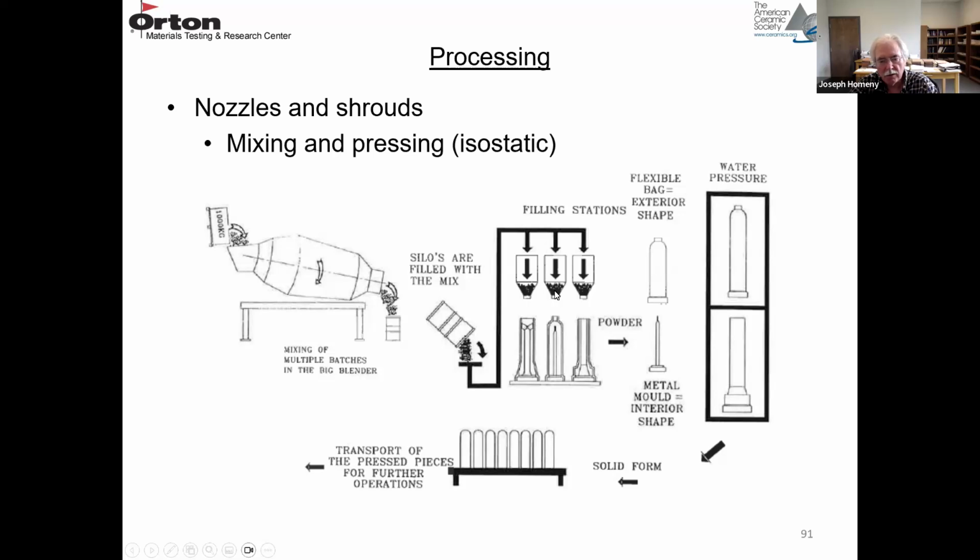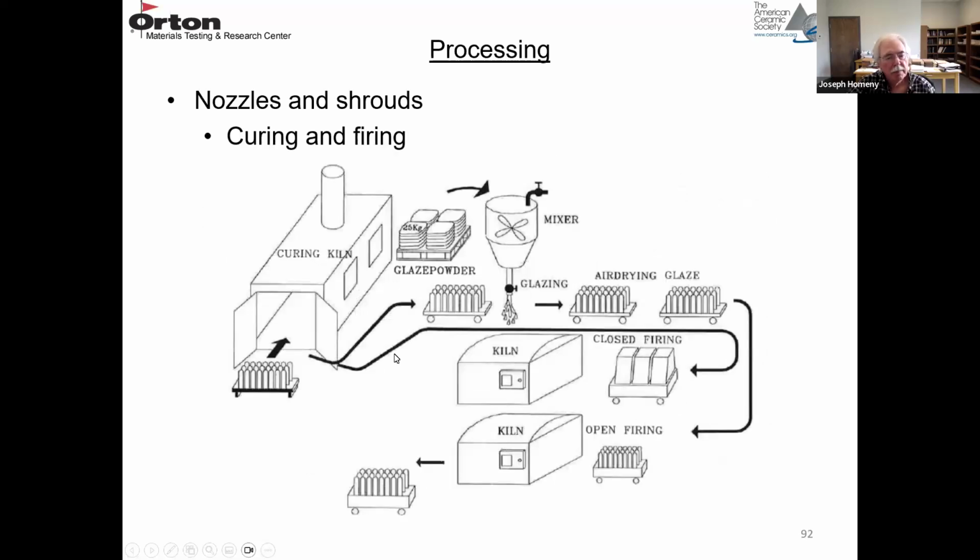And then there's a space here, which is filled with these crushed aggregates or granular material. So once this is filled, pressure is applied either by water or air, and that forms the tube around this metal mandrel. So you remove the mandrel in the bag, and you end up with these tubes. This one just shows tubes with a top on it from the way it's processed. Obviously, that has to be removed for the application.